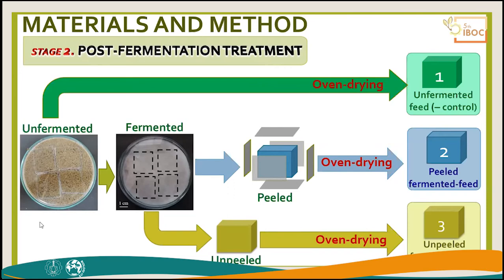And then we did 3 different treatments. The first treatment is that we didn't do fermentation. We just directly do the oven drying, so the sinking feed without any fermentation. And the second treatment is after the fermentation, we peel the surface mycelium. We peel like we are peeling an apple, so we remove the skin completely. And the third treatment is we didn't do any peeling, so we just do the oven drying directly.